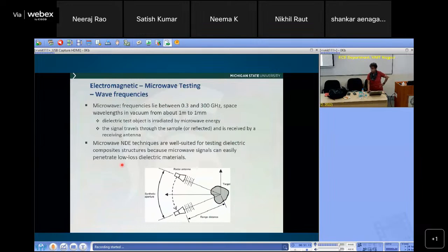So that's eddy current, which is low frequency, and then you have microwaves. Of course, because of the same skin depth, microwaves cannot penetrate metal. So then you have a dielectric sample or composites. Even in composites, glass composites, carbon composites, carbon is conductive, so microwave is not that effective. In principle, the physical principle is very similar to ultrasound. You have a microwave which goes in, it gets reflected just like an ultrasonic transducer, but there's also scattering, the polarization of the E field, the H field. There are differences. In ultrasonic, you have longitudinal wave, shear wave. The underlying physical phenomena are different, right? So again, we'll have a whole day on just microwave NDE, so we'll not talk about it here.